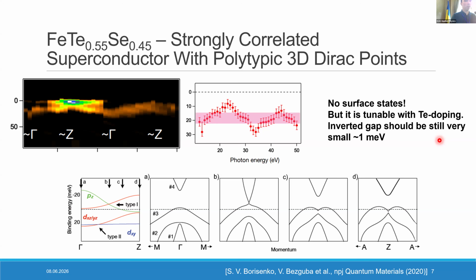It has two Dirac points, one above the Fermi level, one below, of different types, but unfortunately there were no surface states, or at least we couldn't distinguish them, again due to strong renormalization, the inverted gap is becoming very, very small. And this brings us to the next material, lithium iron arsenide, where from theory we know that the inverted gap is several times bigger. So it's already a good idea to check it, because at the very least it should be the same story, and there is more potential for surface states emerging there.